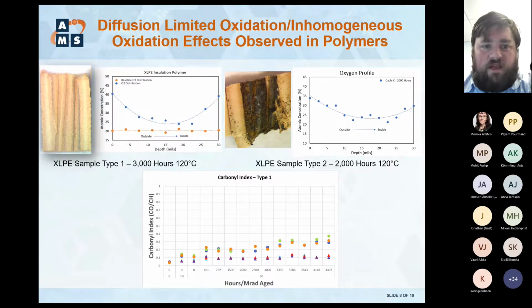We've taken SEM EDS data showing oxygen profiles from a cross-linked polyethylene aged to 3,000 hours at 120C. You can see the distribution of oxygen based on atomic concentration. The orange plot in the left plot shows the baseline distribution of oxygen through this sample. The blue plot represents what the oxygen profile in the polymer looks like after 3,000 hours at 120 Celsius. And in the optical image on the left, you can actually see the discoloration, which you expect is indicative of diffusion limit oxidation. You can see the darker edges around the surfaces of the material, the outside and interior surfaces, and then the lighter region in the middle, indicating we have inhomogeneous aging effects going on.